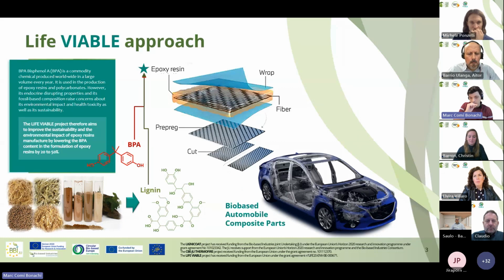So for the Life Viable approach, we selected 4 lignins, which we believe are currently available in Europe. And what we are doing with these lignins is treating them because they cannot be used as such, since lignin is a very complex, aromatic, random biopolymer. We are solubilizing them, we are depolymerizing them in order to make a more defined building block, and we will use this building block partially replacing from 25 to 50% of BPA in the formulation of epoxy resins. These epoxy resins are going to be used to synthesize prepregs that are going to be used in different parts of automobiles.